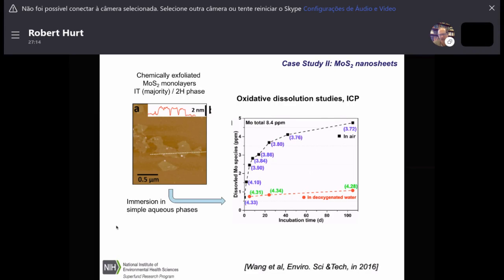If you remove the oxygen by bubbling, say, with nitrogen or argon, if you take the oxygen away from the system artificially, which you wouldn't do in the body but it can be done in the laboratory, these materials retain their stability. So this is an example of a highly insoluble material, but it has an oxidative instability that most researchers wouldn't see unless people studying the transformations of these materials in the human body take a special look under conditions relevant to human exposures. So we believe molybdenum disulfide, although thought to be quite stable, will in fact also be in a class of materials that does not have long-term persistence in the body.